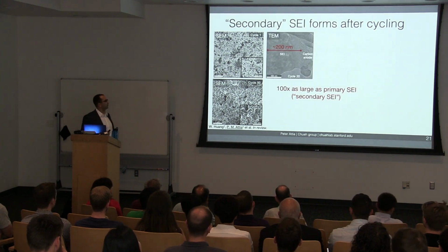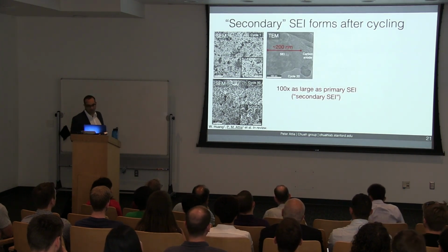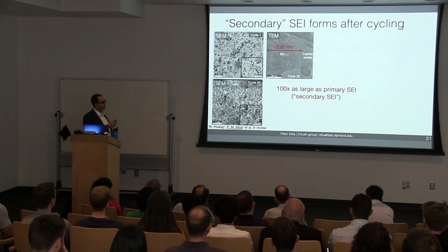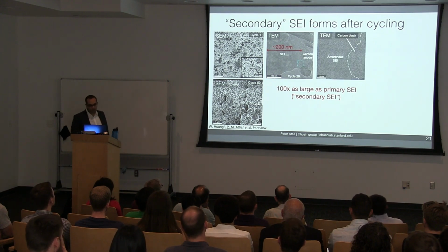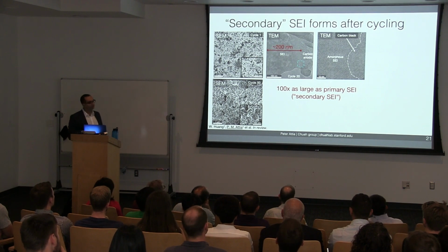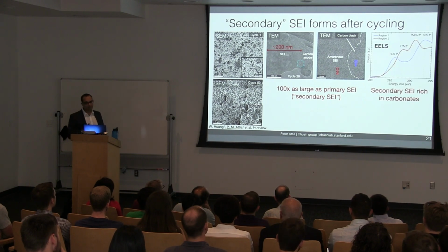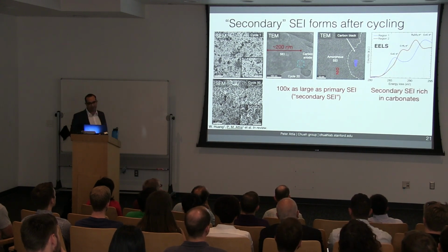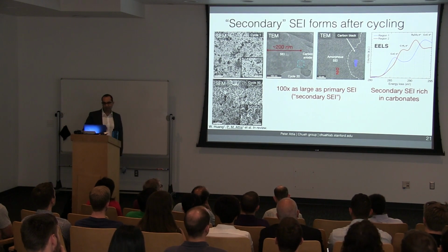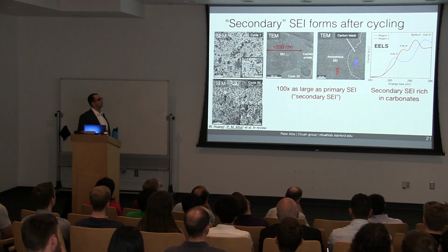We then looked at the electrode with Cryo-EM, and we immediately saw that this type of SEI is well over 100 times as thick as the primary SEI. For now, we're going to call this secondary SEI. And if we look more closely at the boundary between the amorphous secondary SEI and the carbon black, we see that overall it's quite clean. We don't see the inorganic components that we saw before. If we perform chemical analysis comparing carbon black to the SEI, we find that the SEI region is high in carbonates, which indicates reduction of ethylene carbonate.